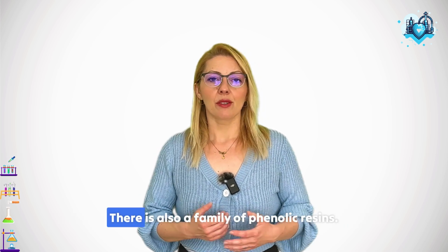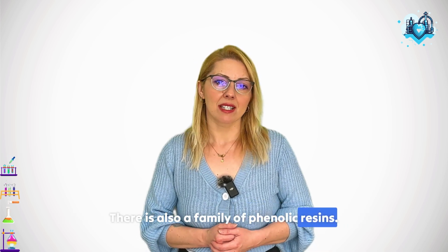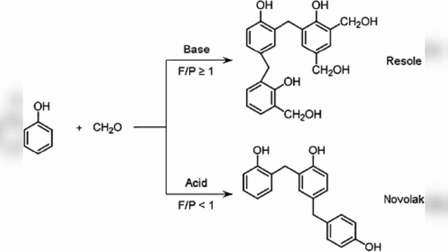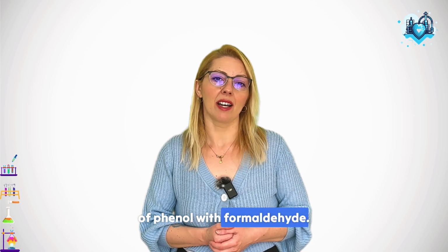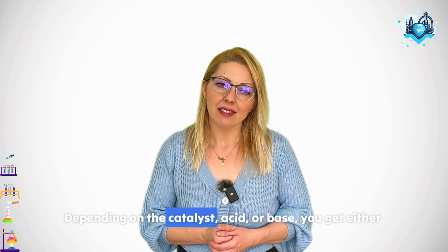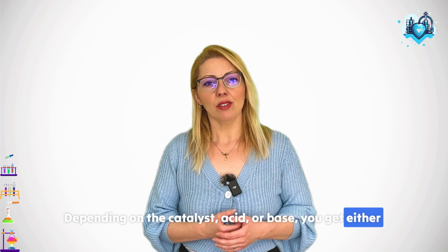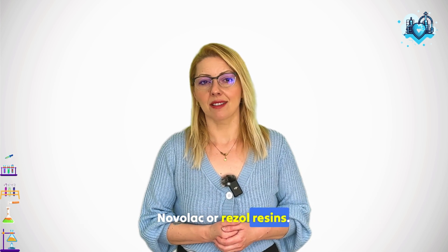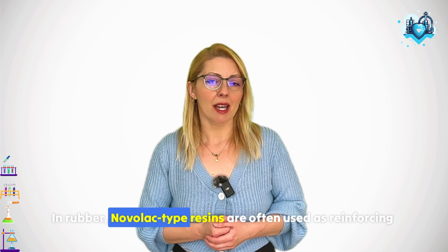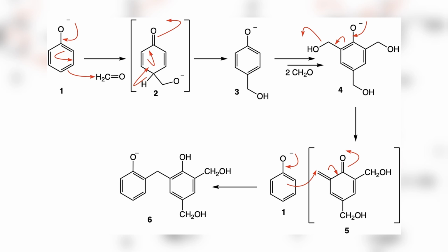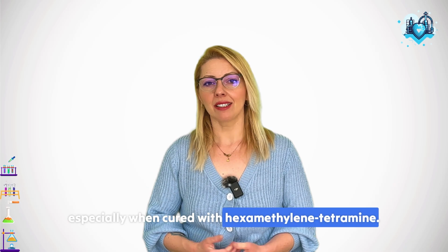There is also a family of phenolic resins, which serve an entirely different role. These are thermosetting resins created by the condensation of phenol with formaldehyde. Depending on the catalyst, acid or base, you get either Novolac or Resol resins. In rubber, Novolac type resins are often used as reinforcing agents, especially when cured with hexamethylenetetramine.